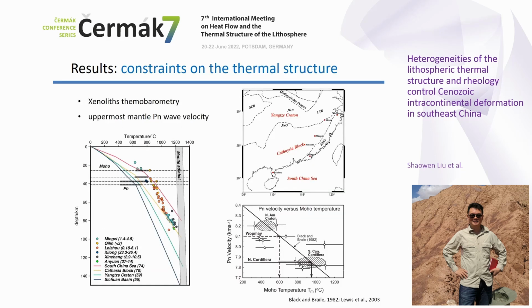We further use other geological and geophysical data to constrain the deep temperature. Here, we show the position of the Cenozoic xenoliths found in southeastern China, which are almost all located in the coastal region. The lithospheric thickness indicated by the xenolith thermal barometers is 60 to 100 km, consistent with our estimations in this region. In addition, the xenolith pressure-temperature points from the mantle fall within the two calculated geotherms of the South China Sea and the Cathaysia Block with heat flow data, indicating that our thermal model agrees well with the xenolith thermal barometers.